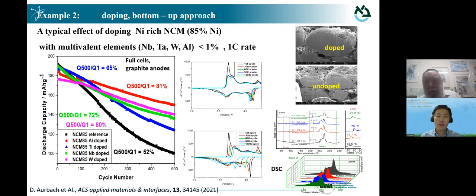So what I show you here is the effect of several doping in full cells. So this is not optimized, but it's well reflective. So during 500 cycles in full cells, this is the reference behavior with no dopant. This is 85% nickel, so the material is very sensitive. And what I show here is high rate, 1C rate. So in lower rate, we can reach nearly 220 milliampere per gram.